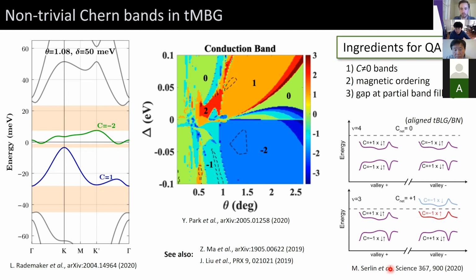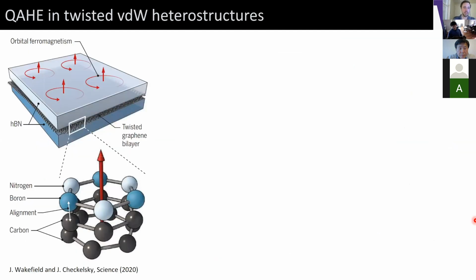So here's a cartoon from Andrea Young's work in aligned twisted bilayer graphene with boron nitride at the magic angle. And they're able to observe a quantum anomalous Hall effect at 3/4 filling of the conduction band. And basically the picture is that you have 8 bands in twisted bilayer graphene, each with Chern index plus or minus 1. And there's a degeneracy of spin and valley. So you have to somehow polarize into just a single one of these bands. And in that case, you would be able to measure within a gap of a Chern band with non-zero Chern index. So those would satisfy all the conditions for a quantum anomalous Hall effect. And indeed, this has been realized.